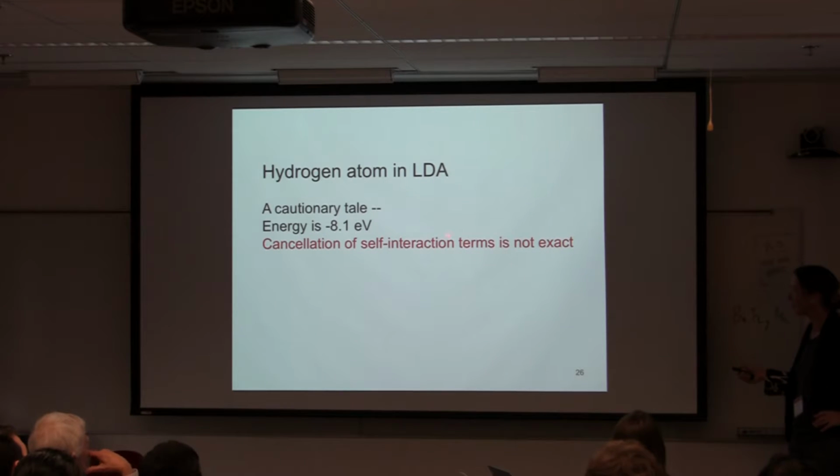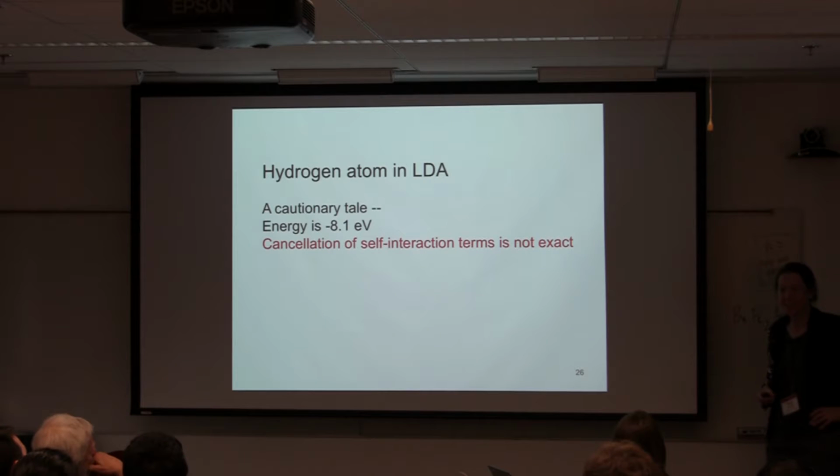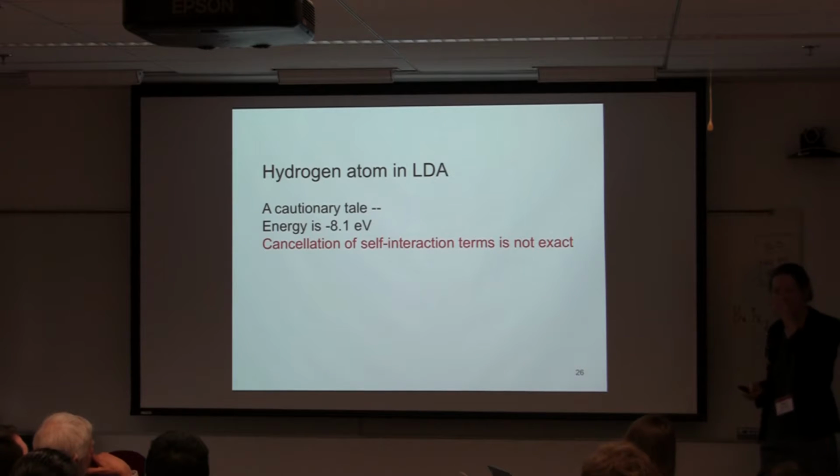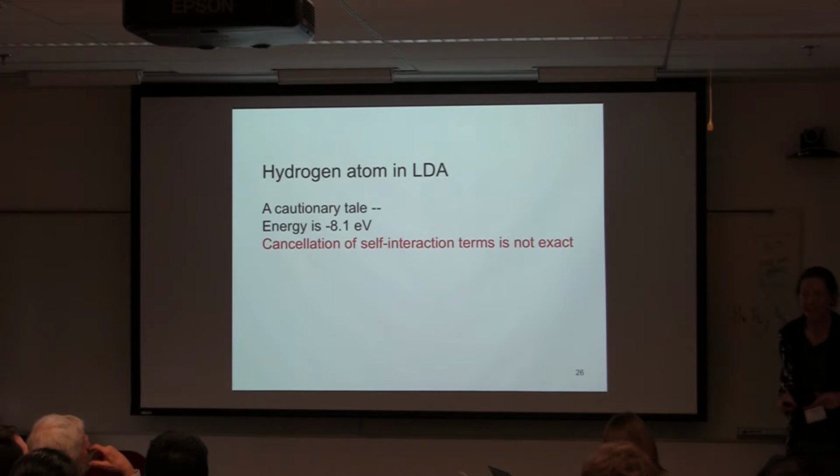And the reason is the self-interaction. The way that I treat exchange in the local density approximation is not exact. And therefore, I have a non-cancellation of self-interaction between the different parts, the Hartree part and the exchange part. And that leads to this disaster.